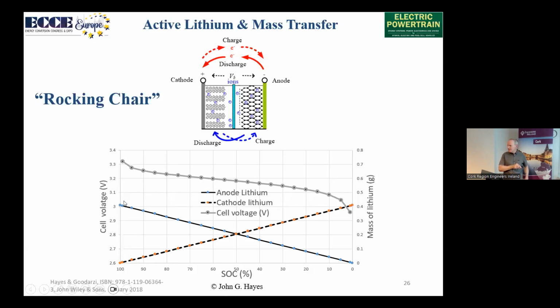As we do a constant current discharge, so we constantly remove the current, the amount of lithium is going to reduce in the anode, and the amount of lithium is going to increase in the cathode, and the voltage is going to reduce. This relationship can easily be described by a log relationship. So when fully charged, the voltage peaks up, and when fully discharged, the voltage starts to sink down. So this would be characteristic of what we call the Nernst equation.